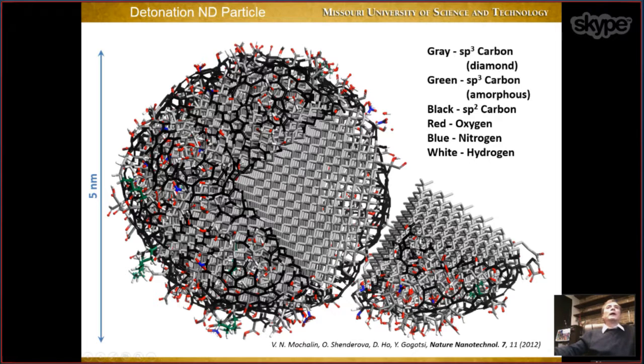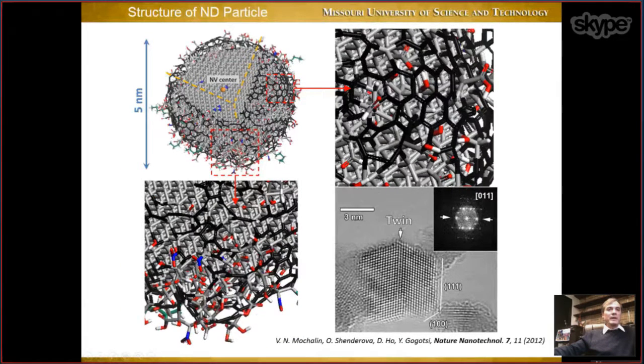Now, if you look closer at the structure of these functional groups, you will see that they are mainly oxygen-containing functional groups, for example, OH, COOH, like shown here. There is also some amount of NO2 groups. Those come from purification procedure, because people normally use nitric acid to remove non-diamond carbon. And this is the structure of sp2 carbon. You can see that sp2 carbon forms patches of polyaromatic structures on the surface of nanodiamond. But otherwise, this material behaves as typical diamond, even shows twins typical for bulk diamond. Twins are special kinds of defects which are typical for bulk diamonds. So nanodiamond also shows them.